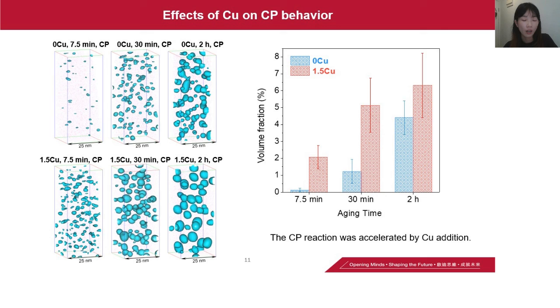And we can see although spherical nickel-aluminum nanoparticles were detected in both alloys, the particles exhibit considerable differences in the particle size and volume fraction. It is apparent that copper addition accelerates and promotes the continuous nickel-aluminum precipitation. The CP reaction was accelerated by the copper addition.